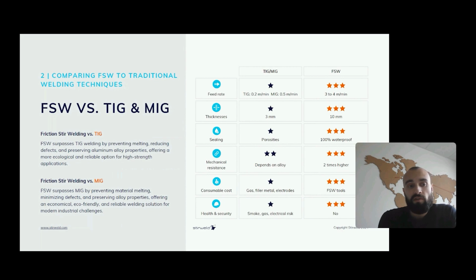But the main difference between friction stir welding and TIG or MIG rather lies into the physics of the process, because in friction stir welding, we won't go over the fusion temperature of the material. We will remain under this fusion point, whereas in TIG or MIG, we have to melt the parts to make the weld. So in friction stir welding, we remain solid into the joint during the weld, and that's why it gives the following advantages. First, about sealing, we do not have problem with hydrogen avidity of the aluminum when welded. That's why we are 100% waterproof, whereas on TIG or MIG, we might have some porosities that are hard to manage.